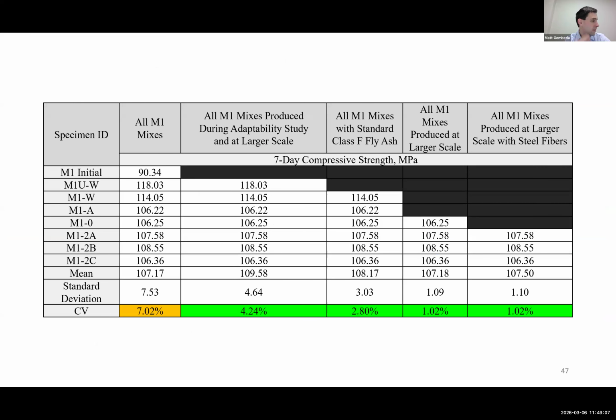Here's an interesting study that we did that looked at calculating some of the statistics. So the goal here was to calculate the coefficient of variation considering all these different variations that we did in the mixes. So the first column is all of the different mixes with the different scales, the cubes and the bigger scales, and all of the different changes in the fiber dosage and all that stuff. So there's not consistency there, but it's done on purpose to just see what the overall COV was across everything. And it was about 7%, which isn't terrible.